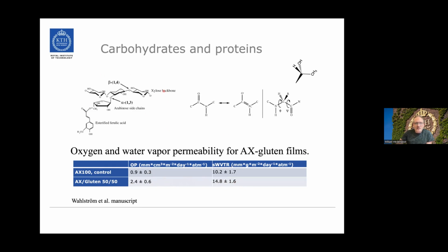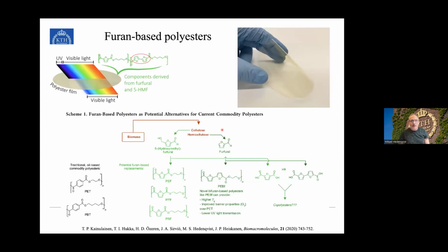So it's interesting to see that this type of structure is actually more effective in stopping, for example, oxygen than the protein structure. The protein has this peptide bond, which actually behaves like a double bond. So this unit is very stiff, but the carbon sitting next to it is very flexible. But you also have these big side groups that would reduce the mobility. But nevertheless, it seems that the polysaccharide beat the protein here.